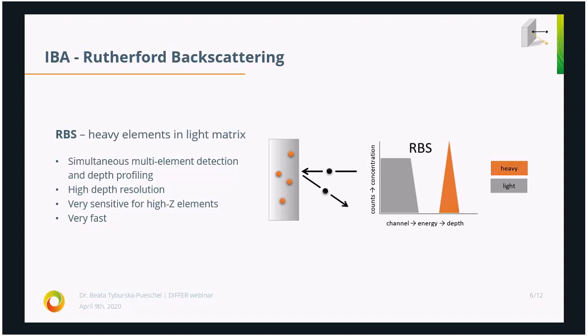For example, tungsten on carbon. Here you have a drawing of it, more or less what it should look like. We have a beam coming from the accelerator. It is backscattered from the sample. Here we have a light matrix, let's say carbon, and the orange particles are, for example, tungsten. And this is more or less a spectrum which you should register. So here the gray is again the light matrix, and then you have a heavy orange peak coming from, for example, tungsten. So you can use this technique to simultaneously detect many elements and to perform depth profiling.